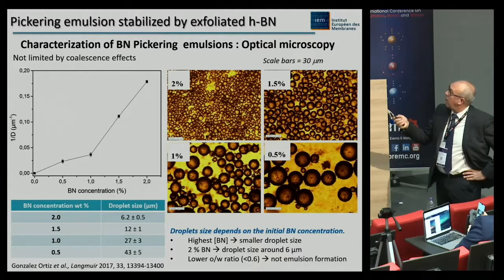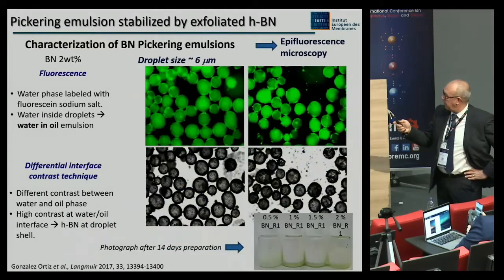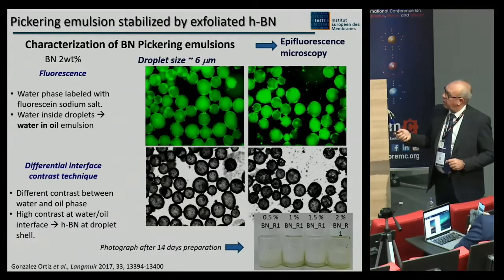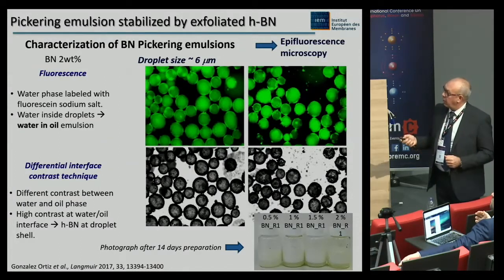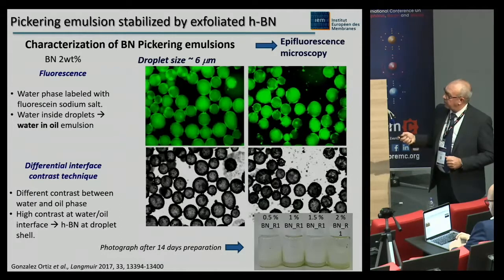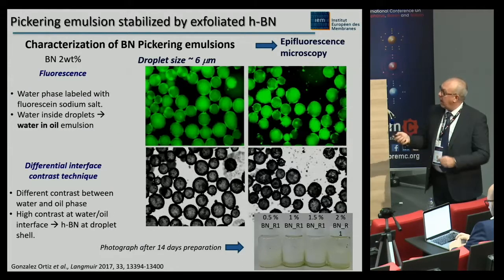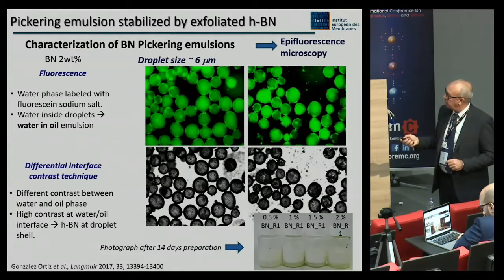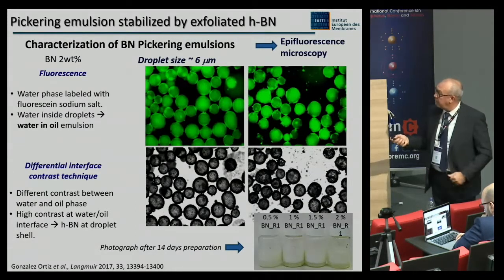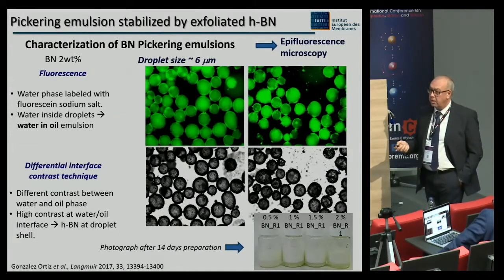So this has been done by optical microscopy, and if you want to characterize the two phases, it's very easy to use epifluorescence microscopy, with a fluorescein sodium salt, which is soluble in the water. This way you can see, because the droplets are very fluorescent, that you have a water-in-oil emulsion at this stage. If you use a differential interference contrast technique, you can also show that you have a very good contrast between the two phases, and also a high contrast at the interface, showing that you have a lot of the BN at the interface of the droplet. And these are some images showing the stability of the emulsion. For example, 14 days after the preparation, the emulsions are still stable.